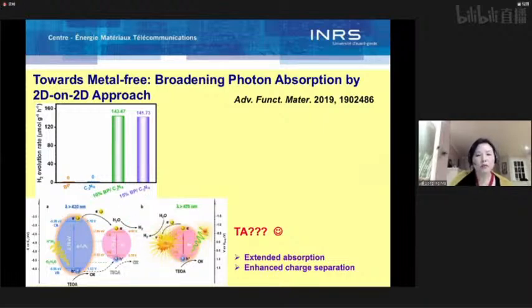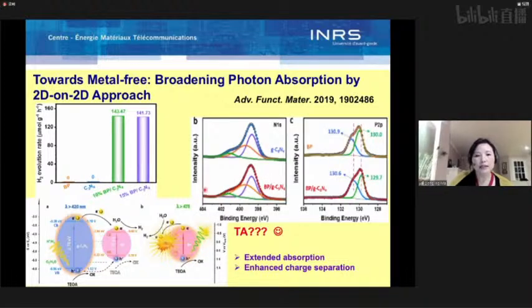To answer this question, we did chemical characterizations. We found that at the interface between BP and C3N4, they form a kind of interfacial bonding between nitrogen and phosphorus. These interfacial states serve as a charge separation site to enhance the charge separation. Basically, electrons can go to this shallow trap site to suppress charge recombination, and the holes can be used for photocatalysis. So with this example, I show that by combining BP and C3N4, we can extend absorption, enhance the charge separation, and get broadband photocatalysis.